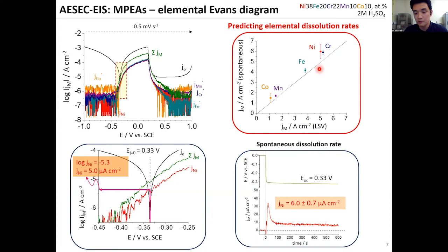In conventional electrochemistry, of course, by definition, open circuit means we cannot really measure the current. But by this technique, we can measure the contribution of elemental dissolution rate converted to equivalent current densities. So it reaches around 6 microamperes, which is comparable to what we extracted from the polarization curve, the Evans diagram here. I did this for these 5 elements. It shows a nicely correlating relationship, which of course is not rigorously one-to-one, but still in a good range. So by this extraction, we can predict the longer-term spontaneous corrosion dissolution rate element by element. That can be significant for understanding the corrosion rate of these complex multi-element alloys.